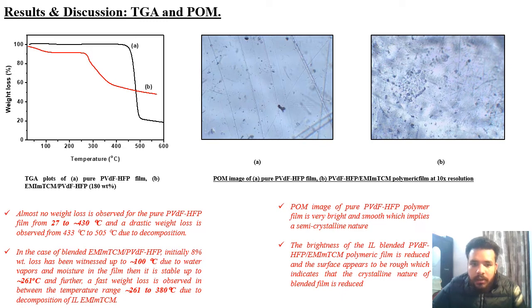In the POM graphs, you can see that the pure PVDF-HFP film micrograph shows a smooth surface, and it is also bright. But when we add ionic liquid inside it, some roughness comes in, and some black dots and black portions arrive, which shows that the crystallinity of the pure PVDF-HFP is decreasing when we add ionic liquid in it.